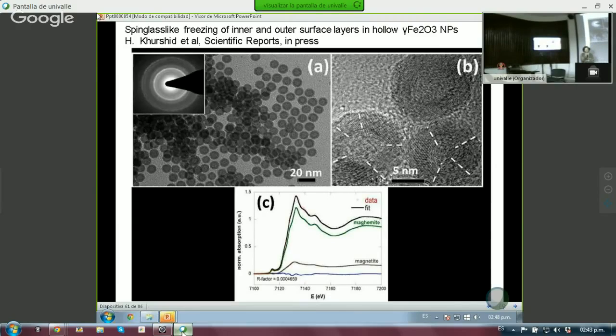And then you take samples that you know of. So you have a sample which you know is 100% maghemite, and so you put it here. And then a sample which is 100% magnetite. And you fit the data accordingly, and you see how much you need of each one to get the best fit. And so it's a standard.